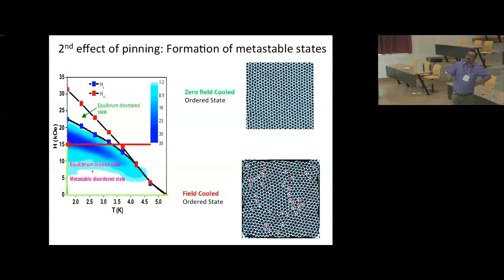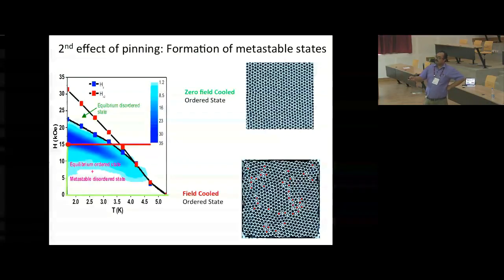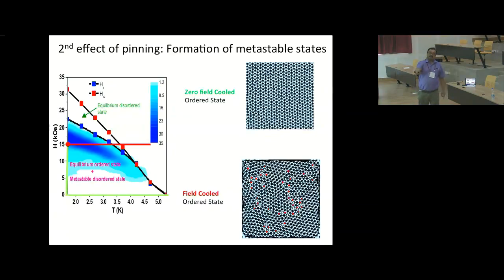Instead, now I go to the same point, but I apply the field at high temperature and then I cool the sample. I get a vortex lattice like this, where all these red and white points are defects. Red is where I have a 5-fold coordination, white is where I have a 7-fold coordination. So you can see at the same HT point, I can have two different kinds of states, and therefore I need to know which one is my equilibrium state.